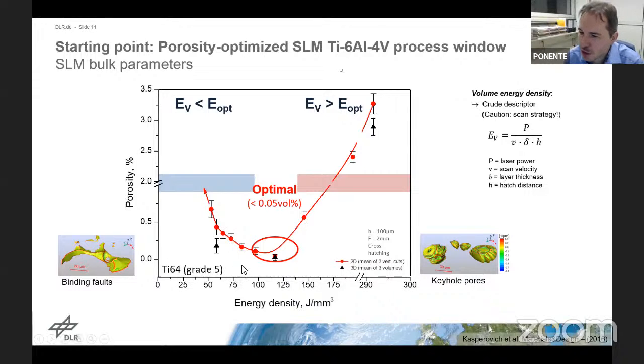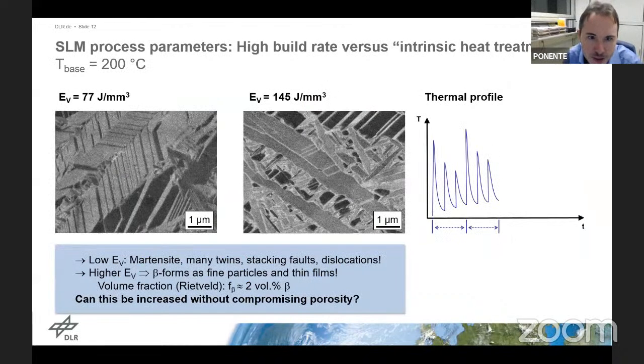And now with a material that's optimized in terms of porosity, we started wondering about the microstructure that we generate with the process here. We picked an energy at the left-hand side of our process window, 77. That's a value that you will recognize in the further slides a number of times. And we picked a processing parameter set with a volume energy density of 145 here. That corresponds to the right-hand side of our porosity-optimized parameter window. It's a little bit higher porosity here, but let's say these border our parameter window. So we asked the question what the microstructure looks like and how we have to adapt the microstructure in order to get proper mechanical properties.